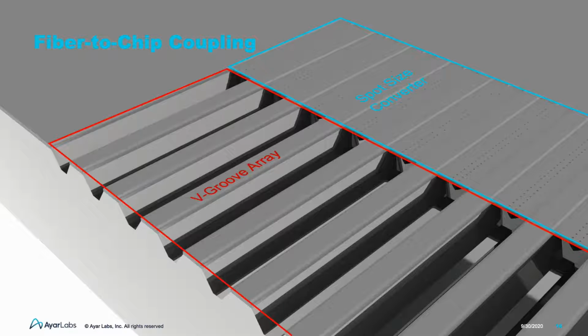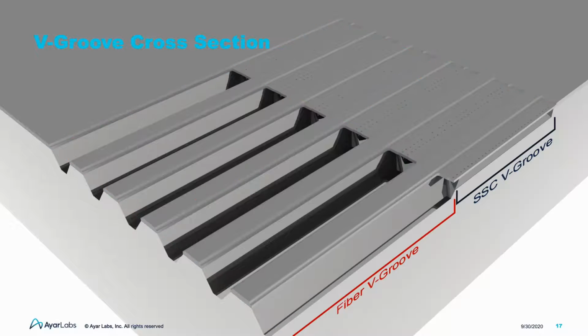This is a zoomed-in view of the same die. The Vgrooves are displayed prominently in the center of the image, and there is one spot size converter for each Vgroove. Let's take a cross-section of the same die, bisecting one of the Vgroove spot size converter pairs. It is clear from this image that the Vgroove is etched into the silicon die. What is also clear is that the spot size converter has an undercut etch below it as well. In other words, the spot size converter is cantilevered over the undercut region.